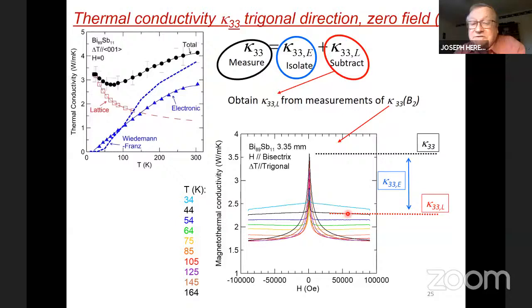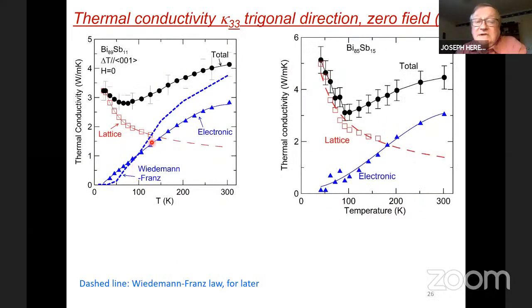These are different temperatures. So basically, the phonon part is the limit for high transverse field of the thermal conductance. The total electron plus phonons is the zero field value, and the difference, we say, is the electronic part. So we do that at various temperatures, and you see here the lattice, here the electronic part, and I'll get back to the dashed line on the next few graphs. All right, this is for a couple of samples. This is 11% samples and 15% samples.